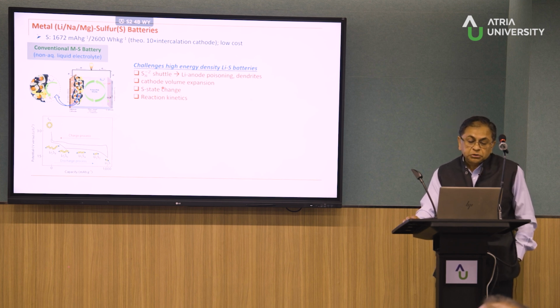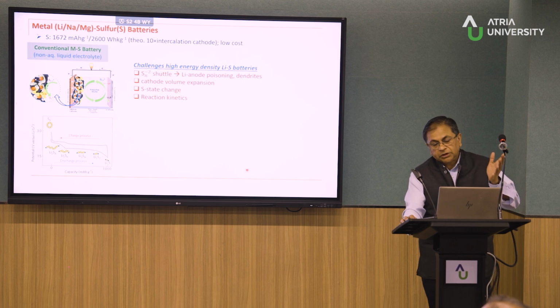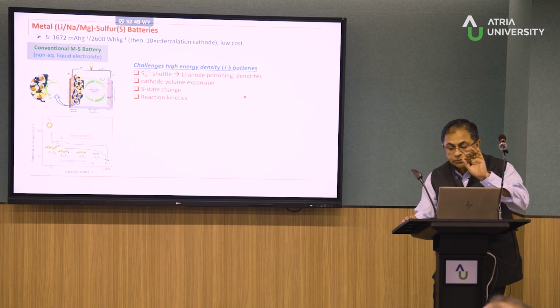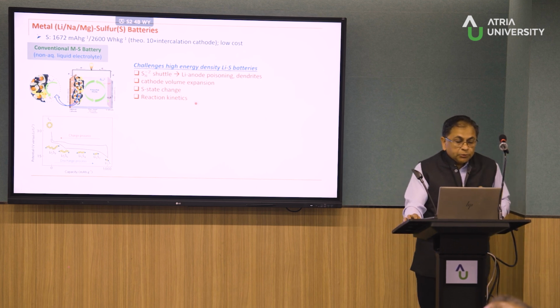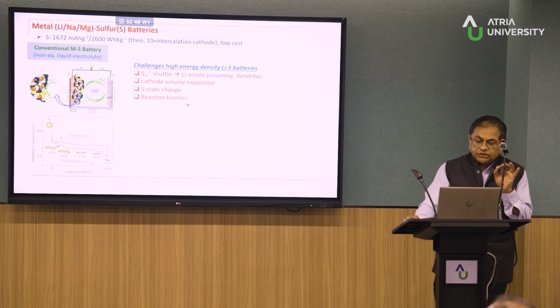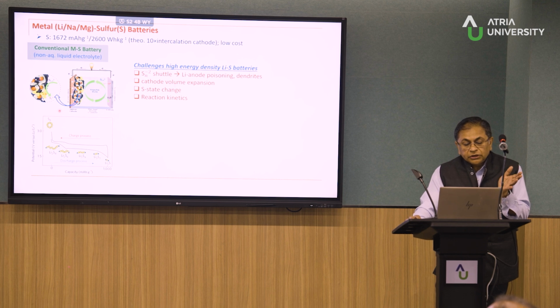And since you are using lithium directly, just like in lithium ion, you have dendrite issues, which is a key issue. Now, again, depending on the dominant ion, if it is lithium, if it converts from sulfur to Li2S, there's a huge volume expansion. It's about 80%. If you take sodium, it could be 300%. So these are the two major issues.